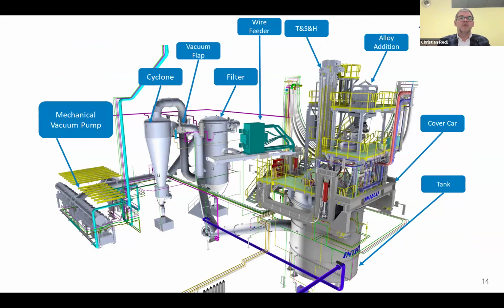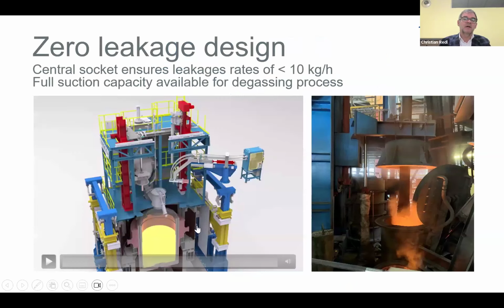Here we see an overview of the plant components. On the left side, the mechanical vacuum pump to produce the vacuum, then there is a filter and a cyclone, because we are sucking off a lot of dust during the vacuum treatment, and this filter system is there not to destroy the vacuum pumps. Then we have wire feeding for very precise alloying of the melt, and a temperature and sampling manipulator to take the samples and measure the temperature at the end of the treatment. An alloy addition system makes alloy additions under vacuum with a vacuum-tight sealing. The cover car, and of course the tank, are the main components of the plant.